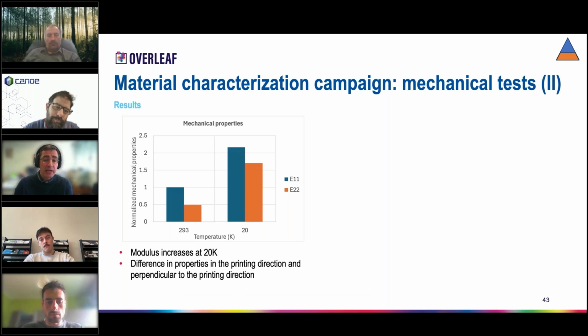From the results, we can see that the modulus increases at 20 K, so this is good for this more stiff, let's say, vessel. But we have a huge difference in the properties in the printing direction and perpendicular to the printing direction. If we look at room temperature, we can see that the transversal modulus is 50% of the longitudinal one. So this can affect the design, because this vessel will be orthotropic. So this is why we have modified, and we don't have a pure, let's say, spherical vessel. So this has had an influence on the results.